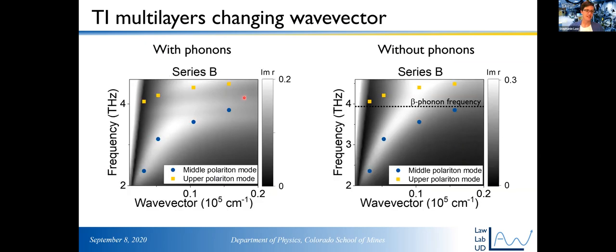And what we're seeing here is actually coupling between the plasmon modes and the beta phonon in this material. So this is what it looks like with phonons. You can see this is our data, matches our T-matrix modeling pretty well. But without phonons, this is what you would expect. Here's the beta phonon frequency, and here's the plasmon frequency. And remember, we talked about this strong coupling earlier in the context of plasmon polaritons. You can get the same thing here. So instead of just seeing one plasmon mode that goes straight through like this, we see a strong coupling, or this avoided level crossing, where the plasmon mode bends over because of the interaction with the beta phonon, and then you have an upper branch here that bends backwards.